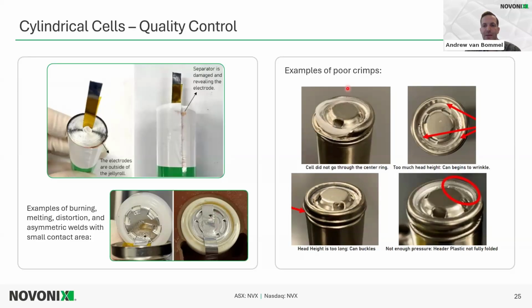And here are some examples of poor crimps. In this case, there could be too much height of that can, so either that can begins to wrinkle or the can buckles. So we see that on the side of the can here. If there's not enough pressure, we can see that the plastic is not fully folded into that crimp. And clearly this one is a fail because that cell did not go through that center ring into the die. So you can see that gasket poking out there.